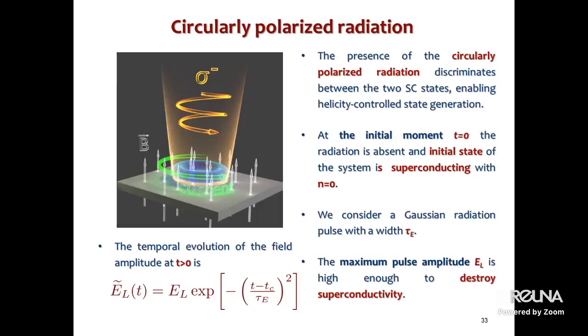So let's investigate the regime where the system was initially in a superconducting state, for example, in n equal 0, so in the 0 mode. For that, we again consider a Gaussian pulse with the switching time tau e. The maximum pulse amplitude is high enough to destroy superconductivity.